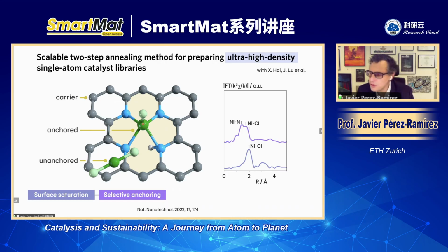Now, if you use this catalyst right now or calcine it at high temperature, you will be in trouble. You will be in trouble because this nickel is mobile. This nickel is anchored, but this nickel is mobile. So that mobile nickel will sinter with other nickel, producing nickel nanoparticles, which is the unwanted process by which, most of the times when you prepare high-loading single atom catalyst, you normally get nanoparticles. So that's why the two-step annealing synthesis method makes sense.